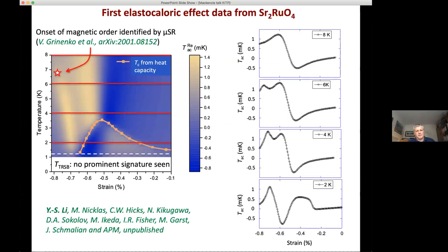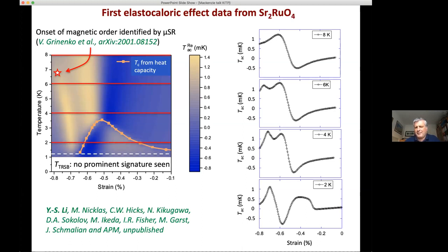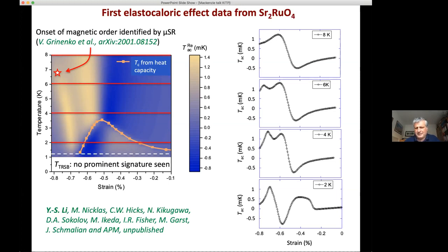This technique is remarkably easy to implement if you are already doing a strain experiment. If you're interested in a strain experiment, you're bound to have a strain derivative of your entropy. Whatever spectroscopy our group does in the future, I would like us to have a thermometer on the sample so that we're getting thermodynamic and spectroscopic data simultaneously. As for whether the elastocaloric effect shows signatures of the time-reversal breaking signal — in the data we have so far, we don't see any convincing signatures. But there's a lot more we can do: we can increase sensitivity, look for dissipation as well as the non-dissipative real part of the response. So we haven't seen anything yet, but I wouldn't convincingly rule out the possibility that we might in future.